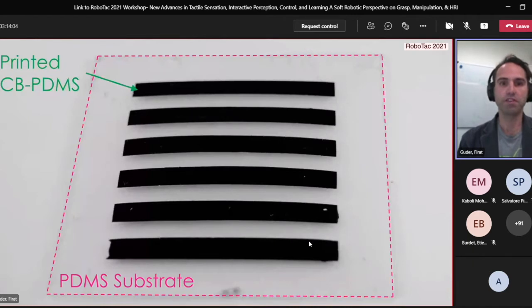And the material itself, once printed, looks something like this. So the PDMS is transparent, so you cannot really see it, but it's printed on a piece of elastomer, this conductive stretchable material. And it's incredibly thin in this case. It's, I think, about something in the range of 50 microns, if I remember correctly.